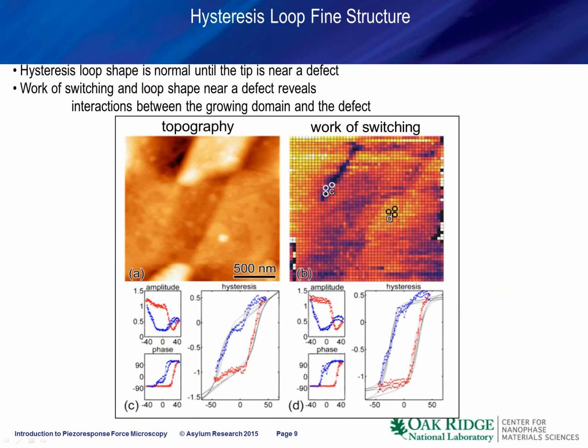For example, shown here is the switching data on the lead zirconate titanate ceramics. And you can clearly see that hysteresis loops at some selected locations have an interesting structure. They have these very fine features. Notice that these fine features are tied to a specific location at the sample surface and not a microscope artifact.